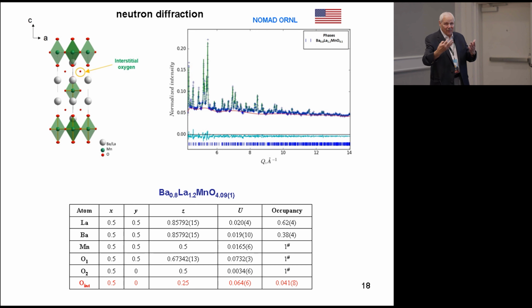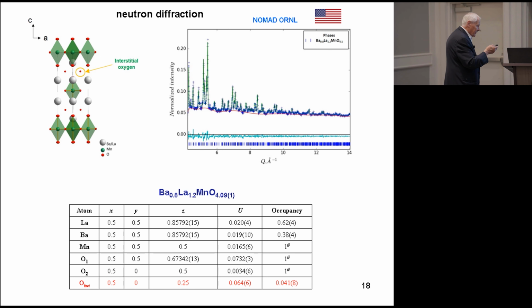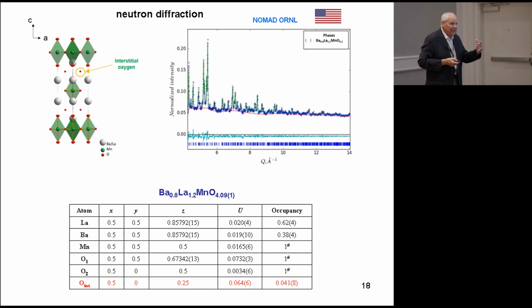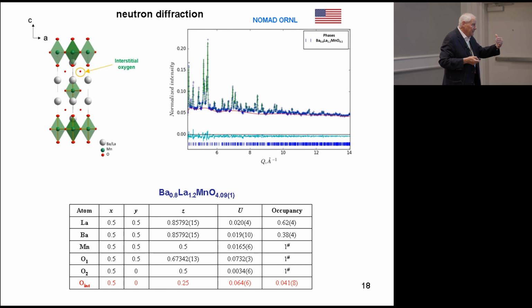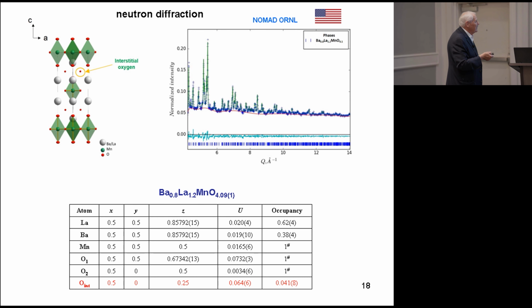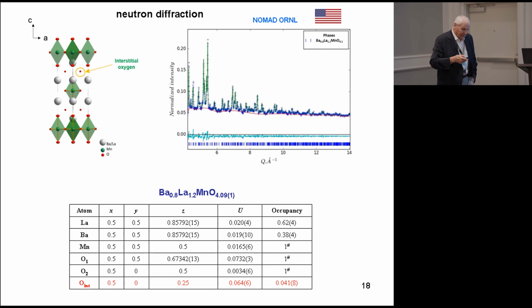NOMAD is, in addition to being a PDF instrument, also a decent powder diffractometer. And the great thing, of course, is that you can collect data out to very high Q, which is very useful in refining occupancies. There was some suggestion from earlier work as to where the interstitial oxygen might go. It goes into that site. She tried that model and refined it just fine. So we have a slightly oxygen-excess